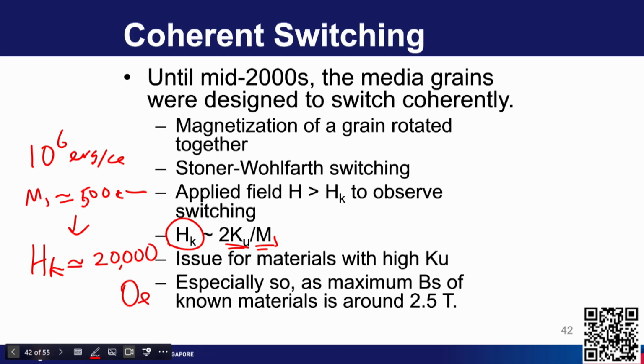Okay. Whereas, the magnetic field that you can produce by winding a coil and inserting a ferromagnetic core, you may be able to produce almost similar value. Okay. So, this is not much more than the anisotropy constant of the material. So, there is difficulty to write information on materials with a large anisotropy constant. Okay. So, writing has always been a problem. So, people are trying to come up with various methods to write information. Okay. So, in that sense, if you follow this coherent switching mechanism, then you have this problem.